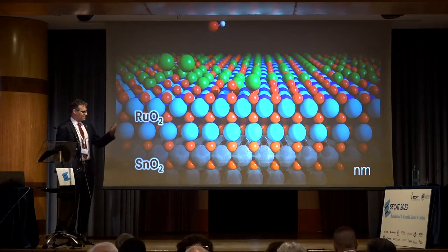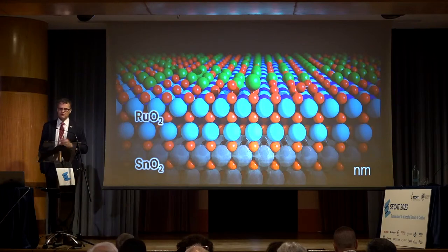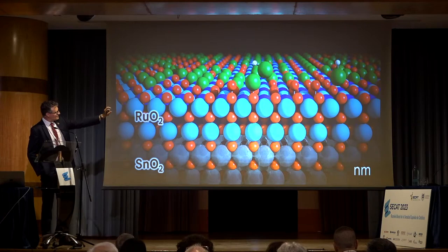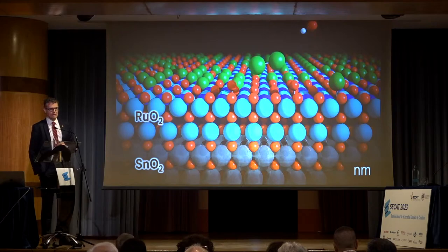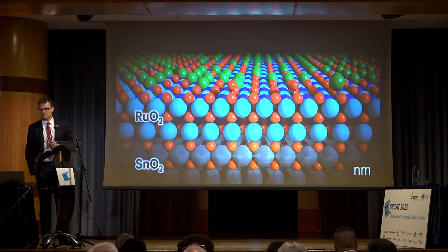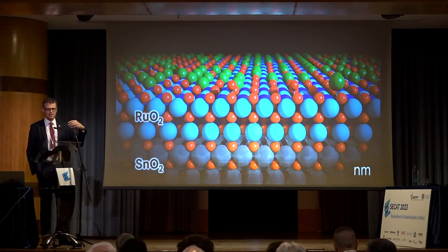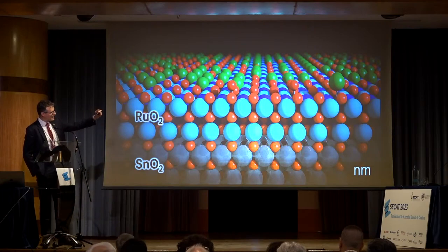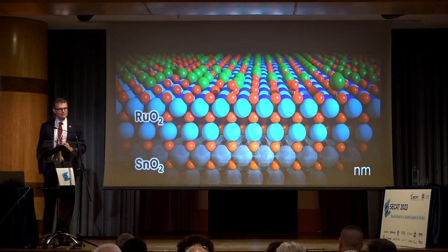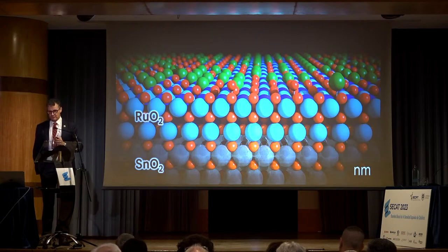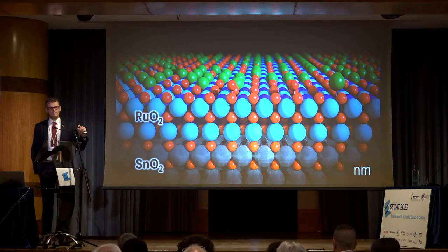And as you can see, this is, of course, an animation, but you will see the reality that the catalyst contains 2 layers of ruthenium oxide. It's actually grown on tin oxide. And that's the only architecture that works for this reaction in a stable manner. That shows the singularity of catalysis. Not every ruthenium oxide on any support will work unless you are able to stabilize a bilayer of ruthenium oxide on tin oxide. Both share the same crystal structure, rutile, so epitaxial growth is allowed, forming a very stable film, which is only of 2 layers.